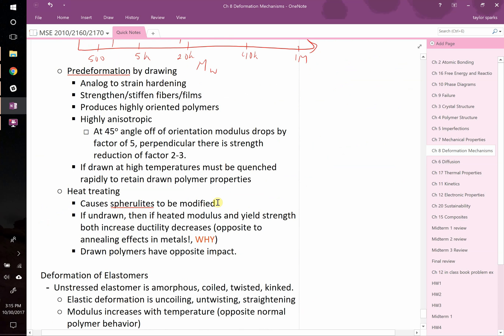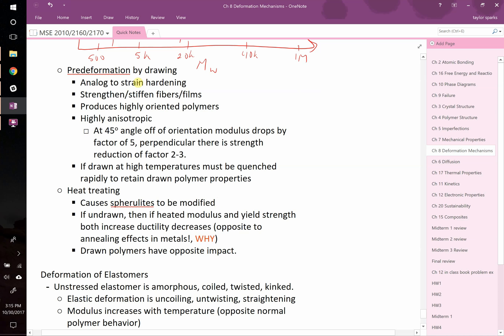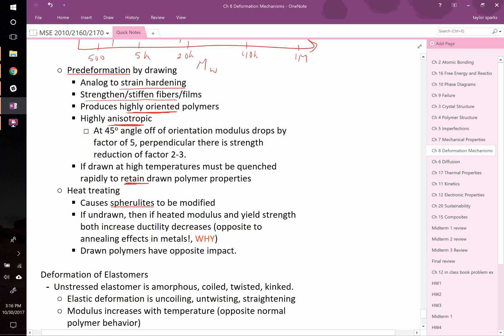Let's talk about deformation in polymers a little bit more. You can do pre-deformation by drawing. You start out with a molten vat of your polymers. You can then grab part of it like you saw in the video with the nylon when they pulled the nylon out and wound it around the rod. This is called drawing and this is analogous to strain hardening. It strengthens and it stiffens the fibers and films. The reason it does so is it breaks up the spherulites and it aligns them along their direction. These highly oriented polymers create anisotropic properties, much stronger in one direction than another. But they're getting stronger and stiffer in this process. If drawn at high temperatures, they can be quenched and you can sort of retain these properties down to low temperatures by quenching them, just cooling them down quickly.